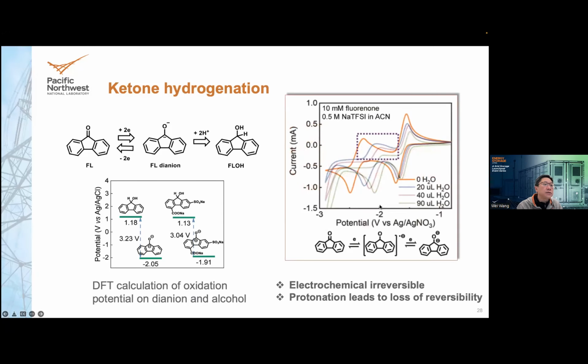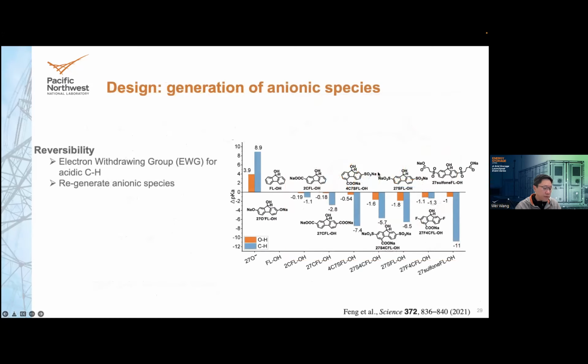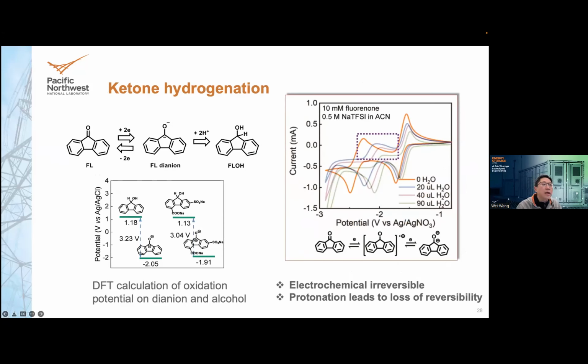What I'm showing here is the CV study. The orange trace is in the acetonitrile without water. And as you gradually add water, you can see those peaks gradually disappear. By the time of the green line, this oxidation peak has already disappeared. So the question here is we need to make this material reversible. And this is very important because there are a lot of organic molecules that have this type of irreversibility, or called partial reversibility.